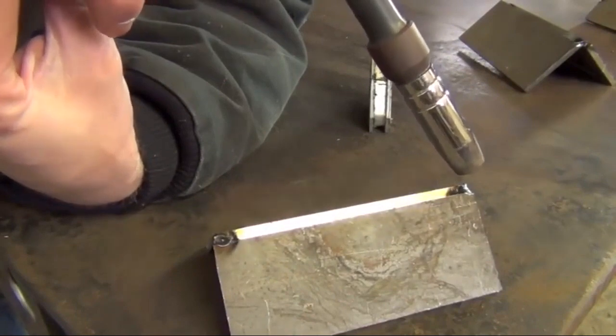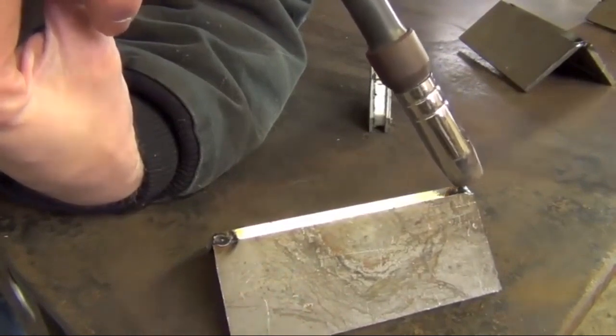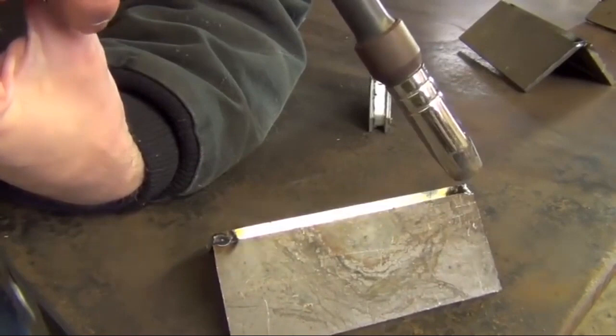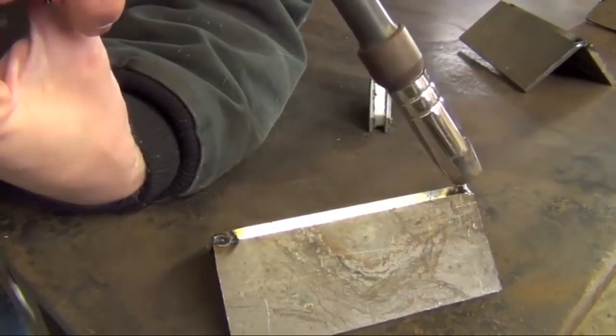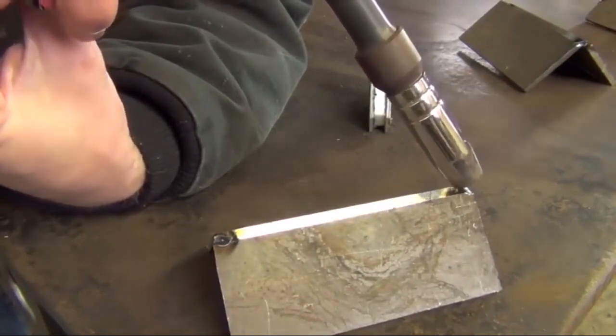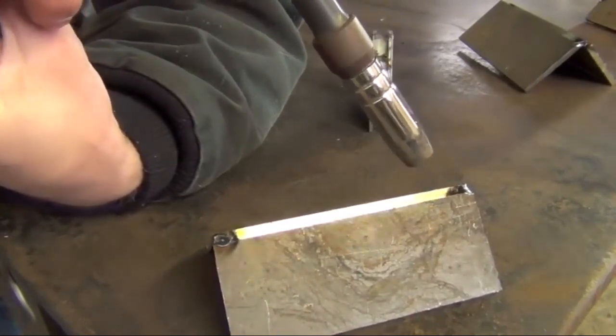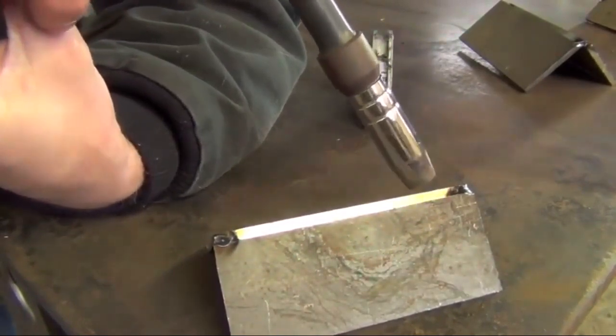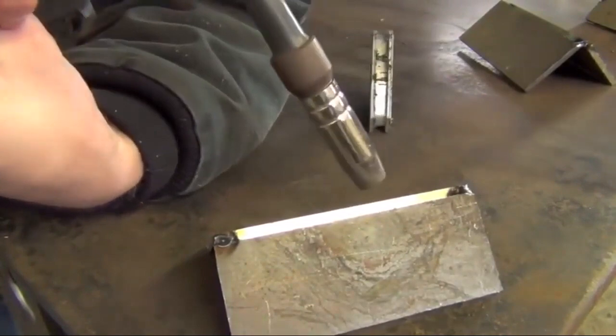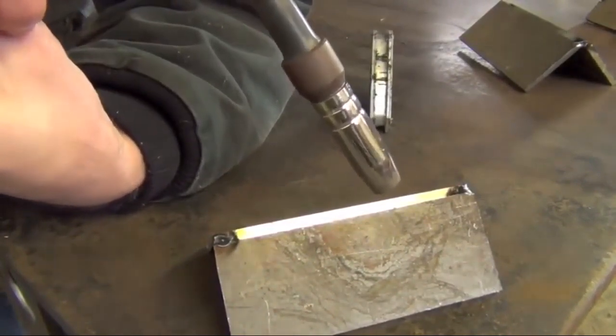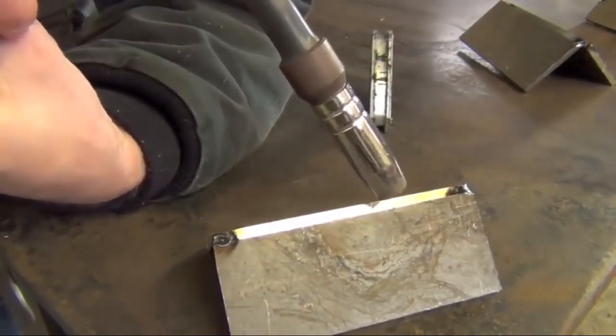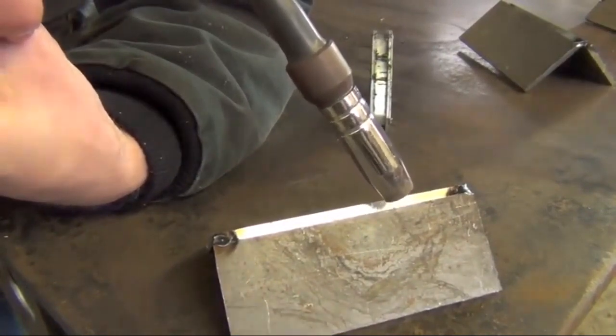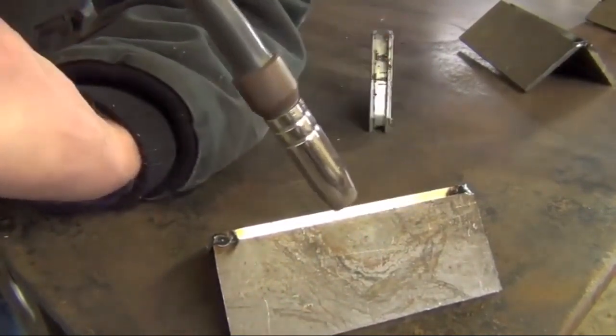And that's a really good way to get cold lap, and to get welds which are even worse than cold lap because they look okay. They actually look good if you don't know exactly what you're looking for, but they're really weak because the metal went on top of other metal as opposed to fusing into the base metal. So that's something you're going to want to keep in mind and actively practice while you practice welding out some joints.